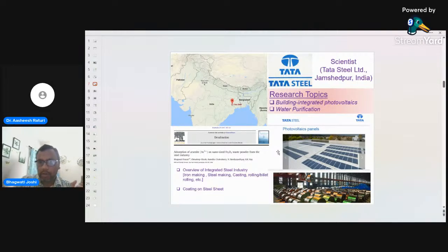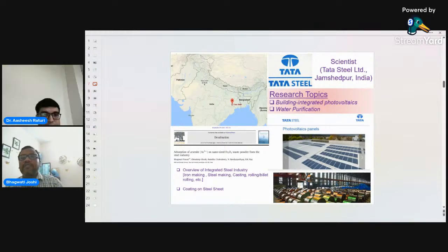that we see for our various applications, including building integrated applications like roof purposes and also for car purposes. You can see down here. So this is what I'm talking about. During that process, when they cool the thick steel slab that comes from the hot roll mill, it forms a thin oxide layer at the surface. Then there is a pickling plant which removes these oxide layers, and it forms thin oxide fines, and one can use these thin oxide fines for some applications.